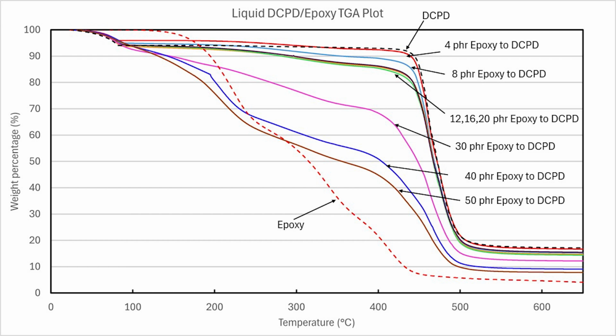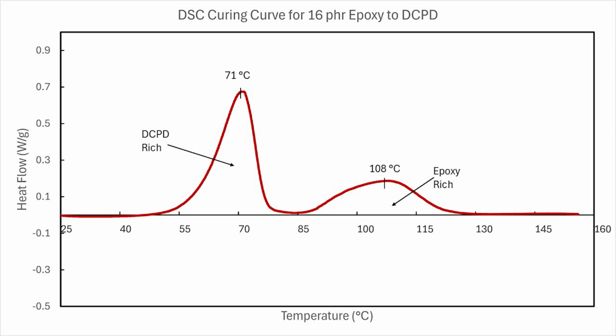We then looked at the volatility of our uncured mixtures as measured by weight loss as a function of temperature. We found that liquid formulations having 12 to 20 parts by weight of epoxy resin per 100 parts of DCPD show relatively low volatility in the range of temperatures we would cure the liquid resin under pressure. In formulations above around 20 parts per 100 epoxy, we saw a sharp increase in weight loss beginning around 100 degrees Celsius, which is below the maximum processing temperature of 150 degrees Celsius. From these observations, we chose to focus on that range of 12 to 20 parts per 100 formulations for the subsequent cure kinetic studies.